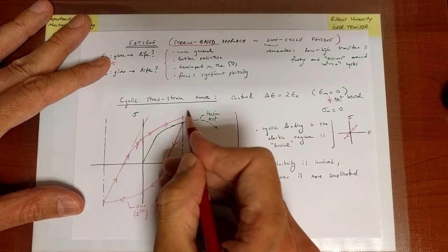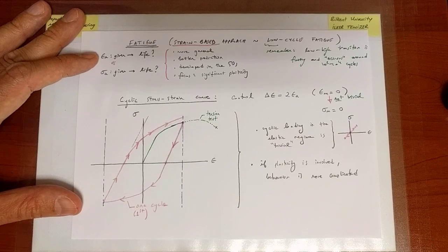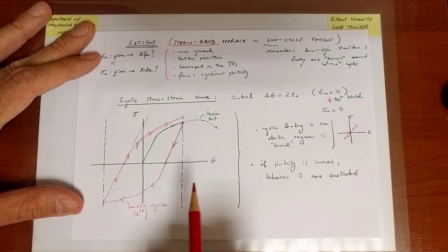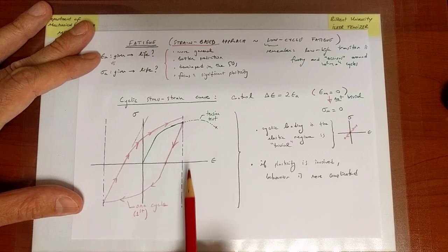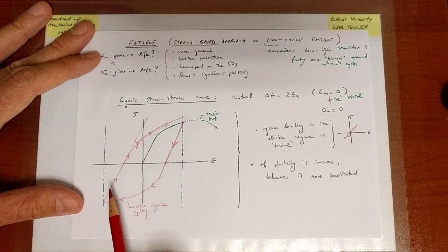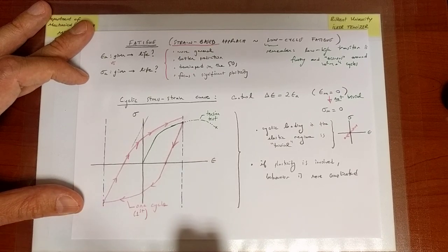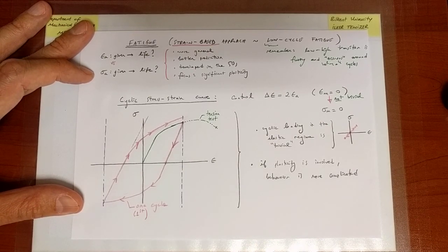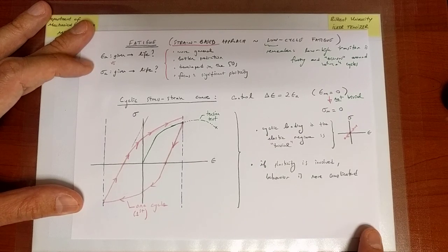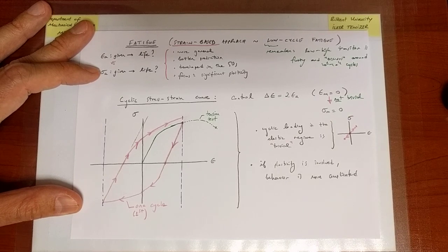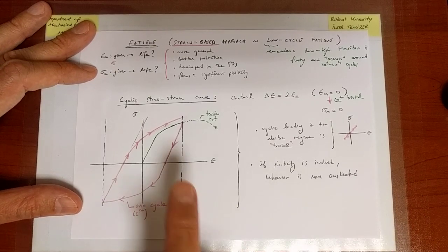In other words, this loop has some area inside that is associated ultimately with, as we've discussed earlier, energy, or work, that is just gone. Where? Into significantly large plastic deformations. And now, if we are looking at such cyclic loading, and if I want to eventually discuss fatigue associated with such a loading, it turns out that the stress-based approach may not be quite suitable. The interpretation is that the stress-based approach is for cases where there is little or no plasticity. Okay, and that interpretation is going to become a little bit clearer further on as we proceed through the